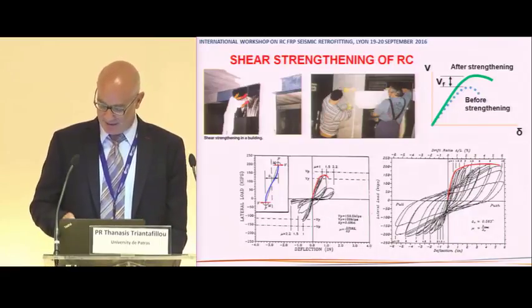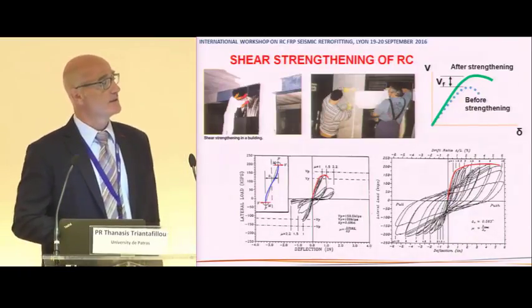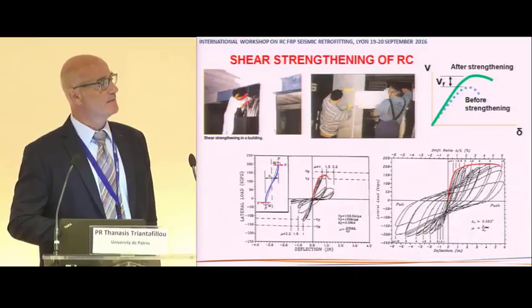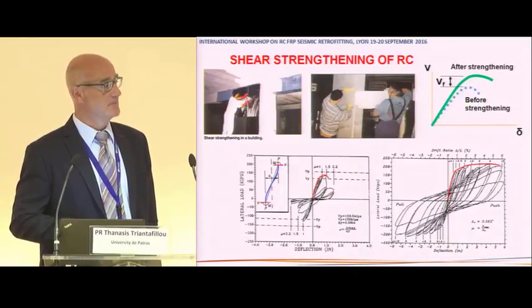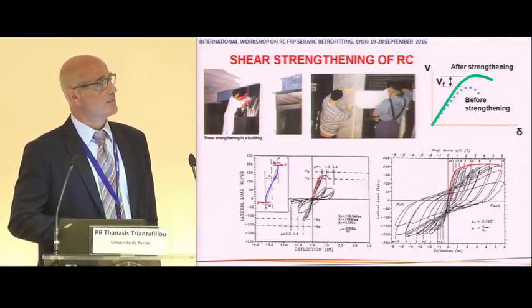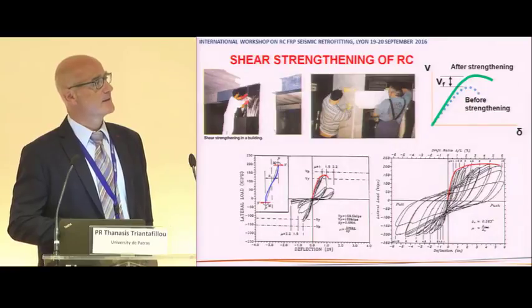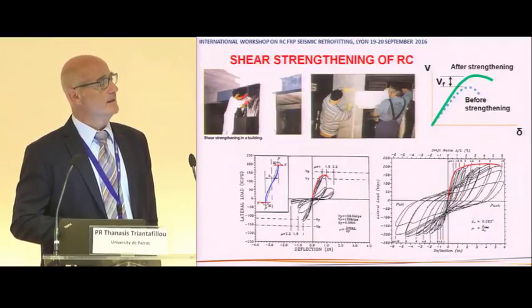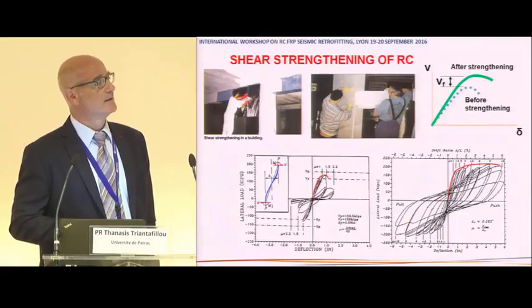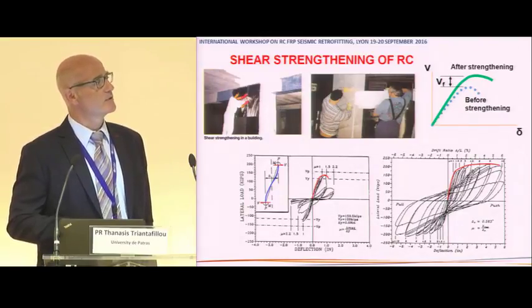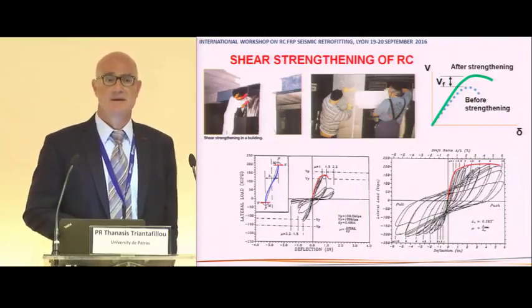When it comes to shear strengthening, the objective of the intervention here is to modify the failure mode from brittle, with very low ductility, to very nice ductile flexural type with stable hysteresis loops. So we practically have to add extra shear resistance to members, and the question is, how do I calculate, how do I design, how do I dimension the externally applied reinforcement to get this extra resistance?